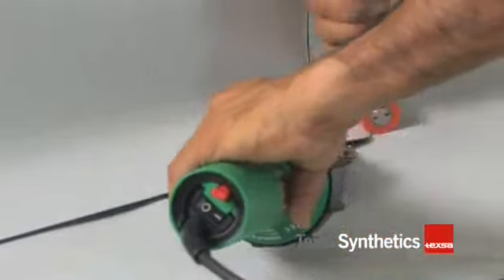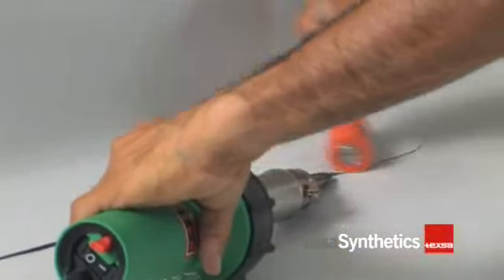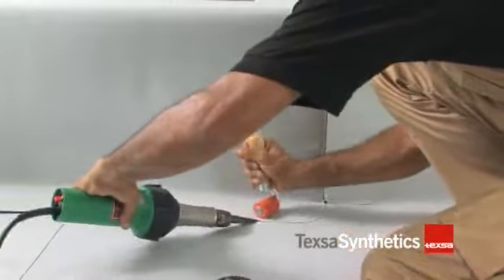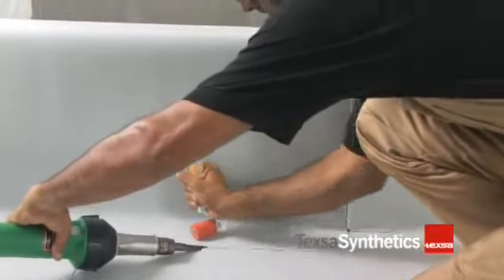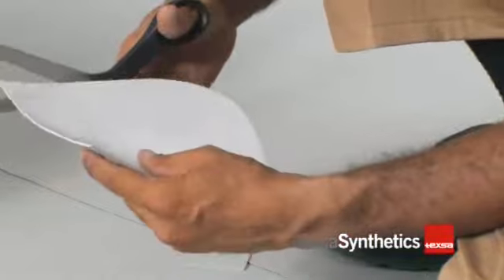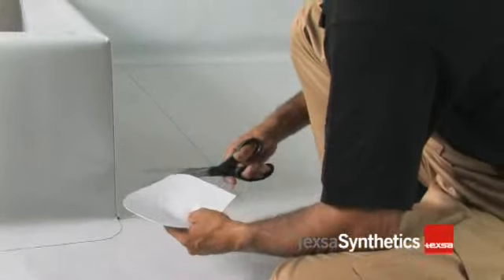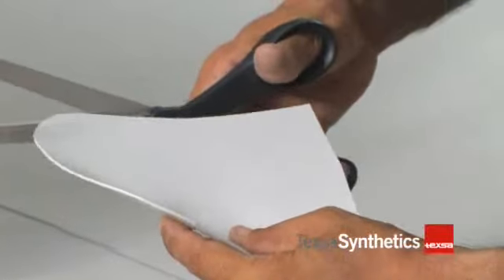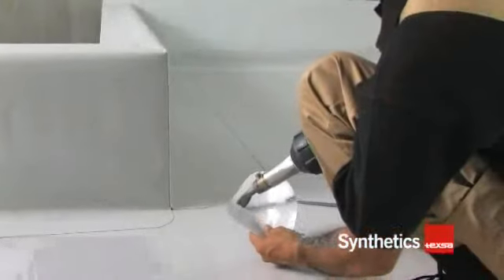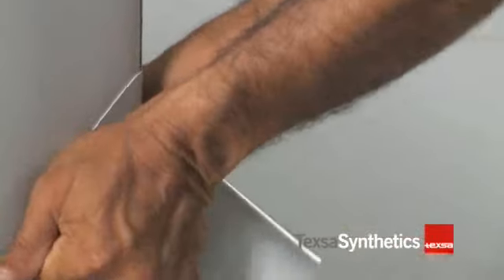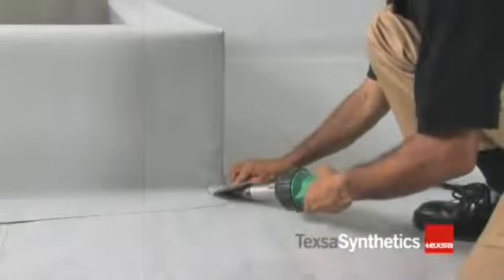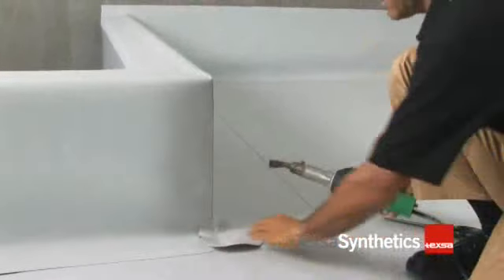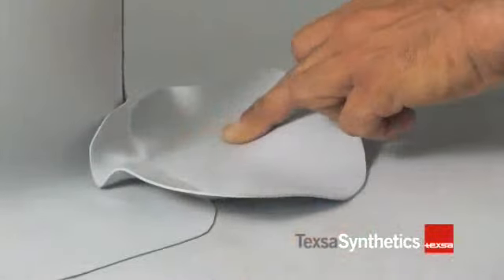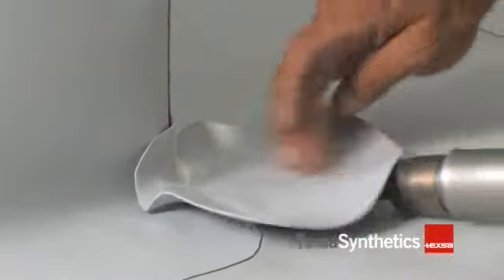To ensure water tightness, place a reinforcement piece along the vertex. The quickest way is to place a piece of prefabricated PVC. If this is not available, it can be made using a piece of non-reinforced membrane 1.5 millimeters thick. Cut a 12 centimeter diameter piece. Apply heat until it is malleable. Stretch it by hand until the appropriate shape is achieved. Position the piece and secure it with a spot weld on the vertex. Then weld the rest of the piece from the inside outward, making sure that no air stays trapped inside.